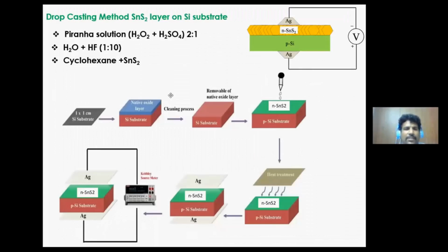Okay. So after getting these three materials, we wanted to know the photoresponse of these materials, because the S0 material is synthesized with only a single solvent that leads to two different materials, SnS and SnS2, and the other two materials have purely different morphology. One is leaf-like morphology, and one is hexagonal flat, and the leaf-like one is disc-shaped. For that purpose, we wanted to construct a photodiode with a P-type silicon substrate, because SnS2 is dominated by N-type. So N-type SnS2 and P-type silicon.